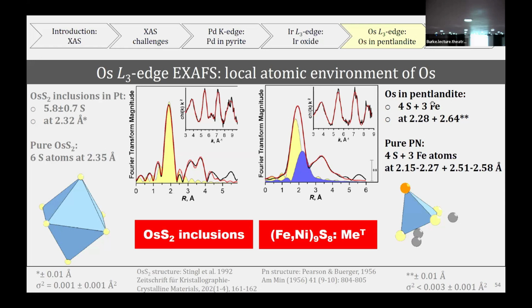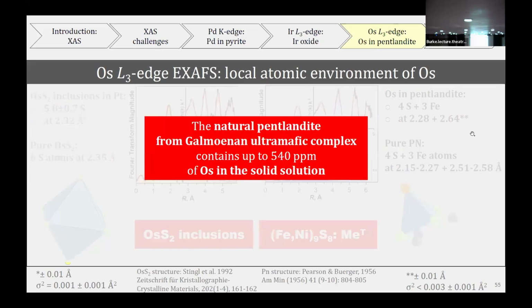Well, sorry. That osmium in pentlandite is surrounded by sulfur and iron in the first and second coordination shells, and the interatomic distances are quite close to the pure ones in pentlandite, since osmium's radius is not that different from iron and nickel. Yeah, and here we've shown that osmium incorporates in the solid solution in tetrahedral state and up to 540 ppm in this sample from Galmoenan ultramafic complex.